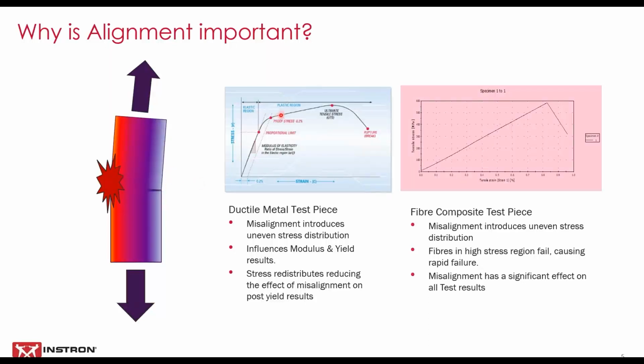Once we're into the plastic area of plastic deformation, we're probably not going to see too much influence of misalignment on that part of the curve, but it's generally the first part of the curve that we're really interested in anyway, and so that's going to be influenced. On the other hand, composites are particularly sensitive to misalignment because they're generally fairly brittle materials, particularly thermoset resin-based composites used in aerospace. The fibers will start to break in the high stress areas, and once the first fiber breaks, you're going to get a fairly rapid failure of the whole specimen. So that's going to influence the UTS and the ultimate stress and strain results.